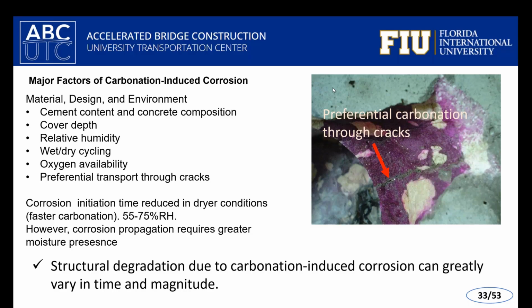At higher humidities, you can develop more moisture within the system, and corrosion is an electrochemical process that requires an electrolyte, requires water. So at higher moisture presence, you can promote these electrochemical oxidation-reduction reactions that cause the damage to the construction materials. Wet and dry cycling in terms of moisture is also very important and is somewhat related to the oxygen availability. Typically for infrastructure systems, what really causes corrosion in terms of the actual reactions that occur is oxygen. Oxygen is the universal oxidizer. The reduction of oxygen typically is the reaction that accounts for the oxidation of the steel and the iron, for example. So oxygen needs to be present in the system.